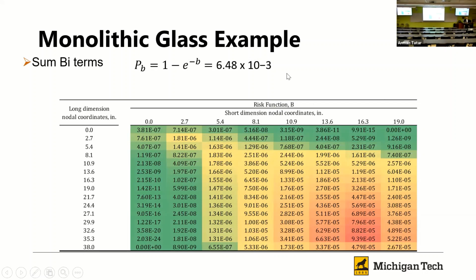In this case, we came up with 6.48 times 10 to the minus 3, which is less than our 8 in 1,000. So this design works. It's close to being maxed out, so its load resistance is probably a little bit higher than 40, but it's not much higher than 40.